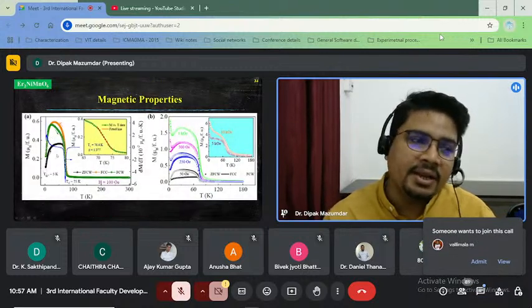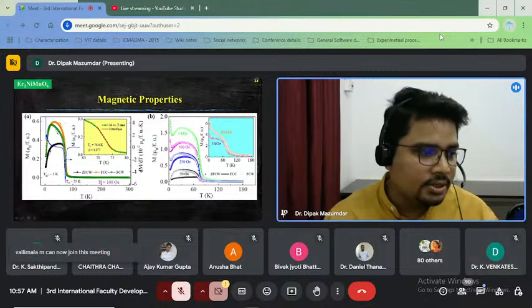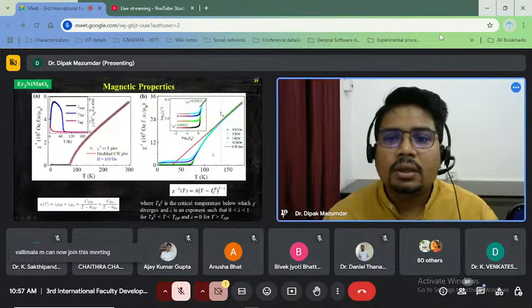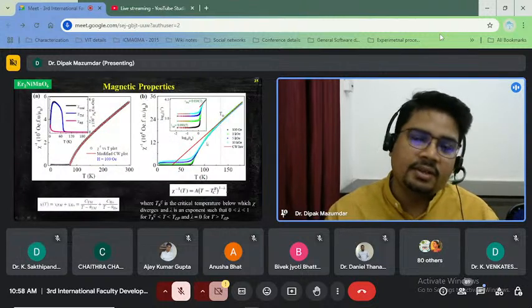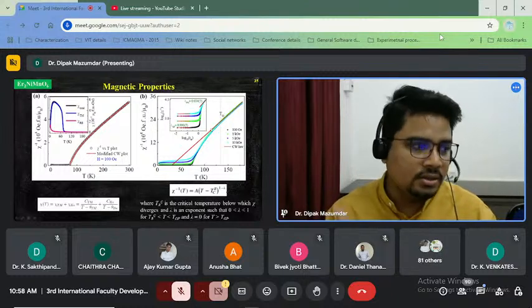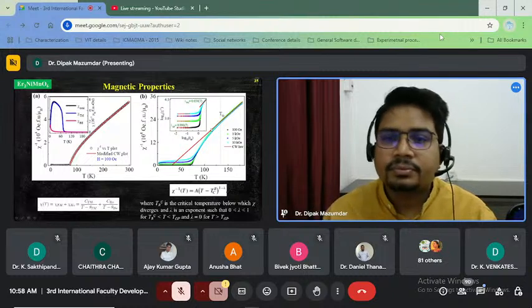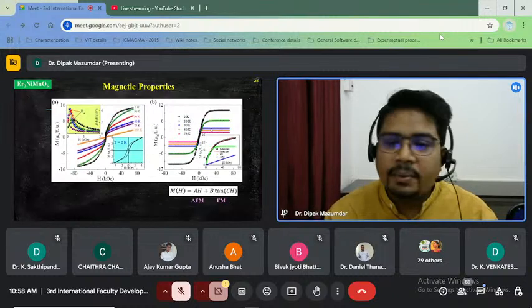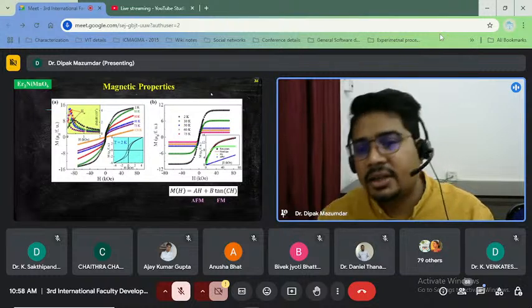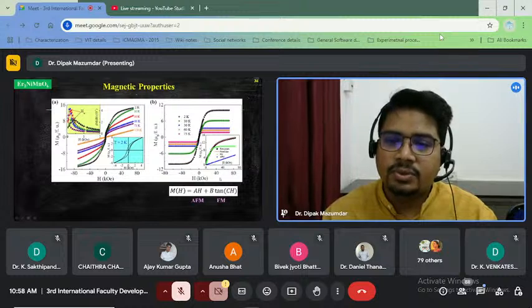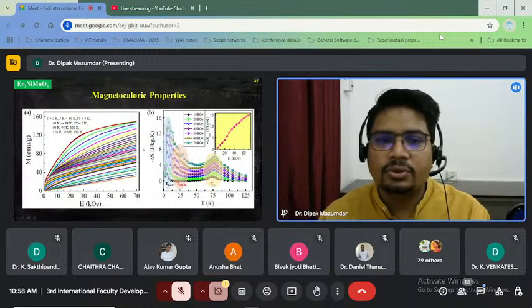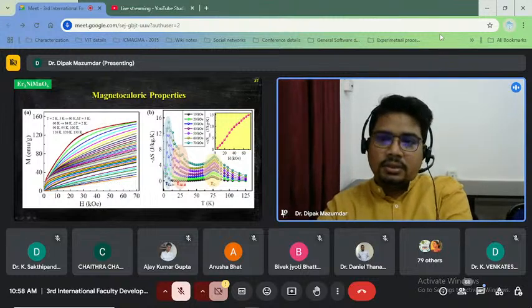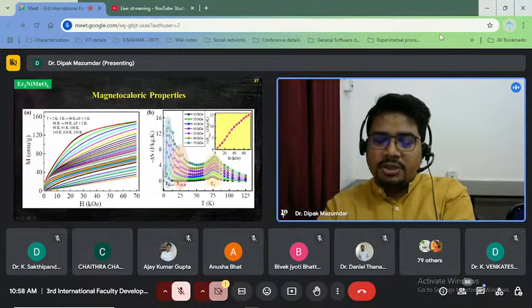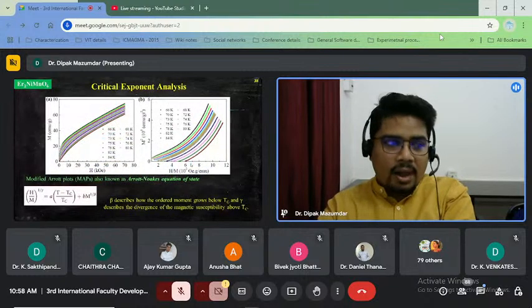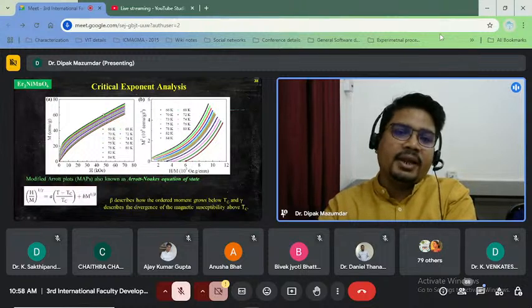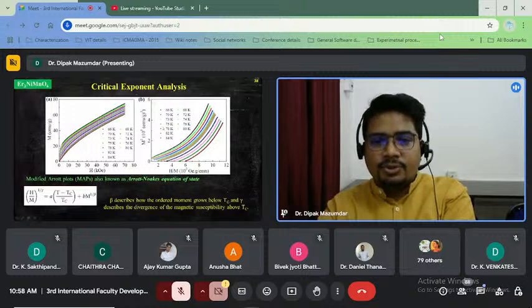Here we can observe a ferrimagnetic transition with application of field. After this, the system also exhibits Griffiths phase-like behavior. Griffiths phase behavior is that above TC, some ferromagnetic clusters form in this compound. Similarly, this is isothermal magnetization, and I have extracted the ferromagnetic and antiferromagnetic parts by using this function. We have also estimated the magnetocaloric effect and dictated the 3 different conditions, which I already discussed for the SCMO compound.